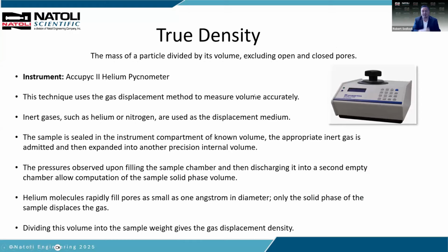Okay, true density, like I said, use a gas displacement system. This will tell you the density of your powder with all the air removed. Then you can take your compressed density divided by your true density and get your solid fraction. Okay, 1 minus solid fraction is your porosity. We need this because it will influence our disintegration and then dissolution.